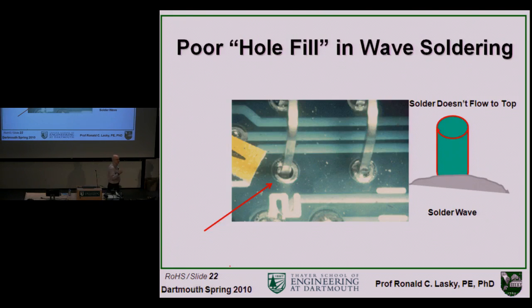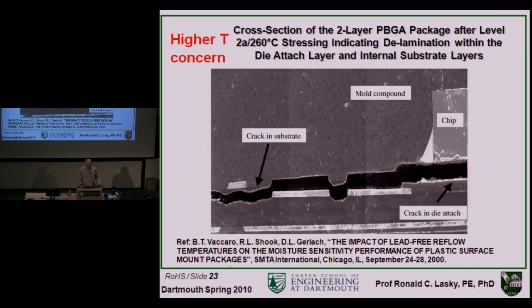Because it doesn't wet as well, it doesn't fill holes as well in through-hole soldering. And I'm not a very good artist, but I think I showed you that in through-hole you have something like this pin that is inserted in a hole in the circuit board. And I tried to show this as a hole in a circuit board so it would have a pin in it. The bottom of the hole goes through a wave of solder in wave soldering. And this barrel of this hole has copper in it. And the surface tension wicks it up, and it should fill the top and form a nice fillet on top here. And you can see that's not happened here. And so that's one of the issues in using lead-free solders.